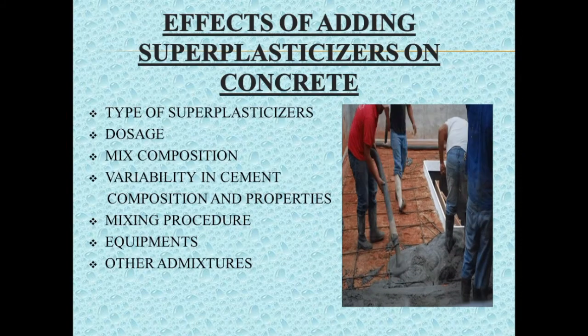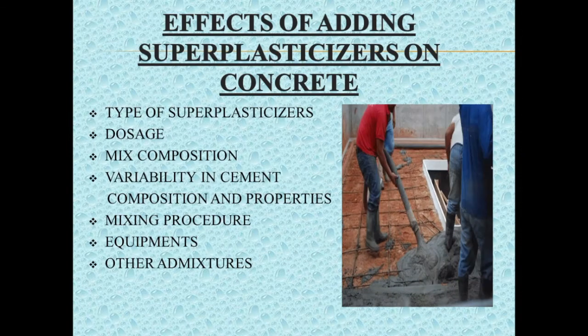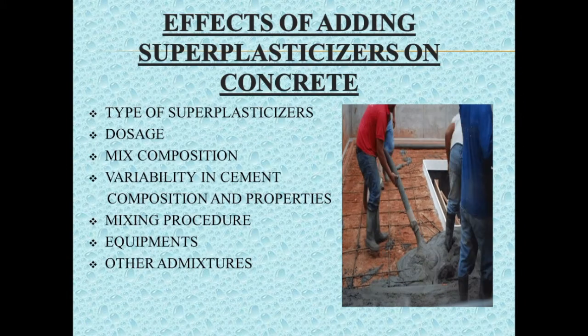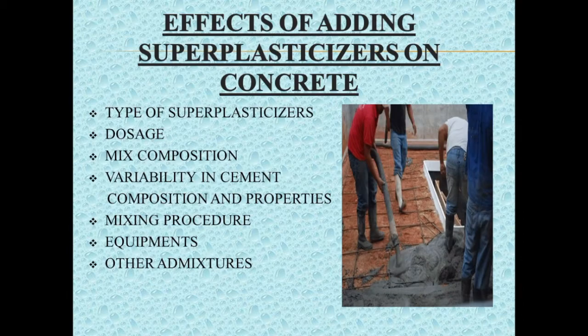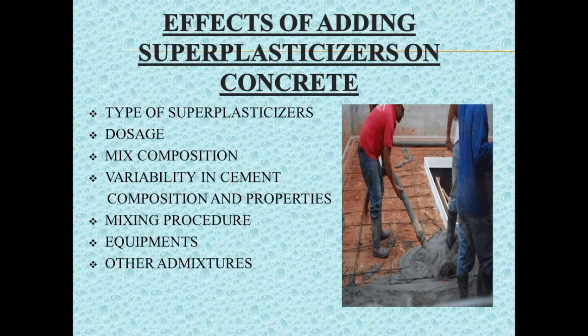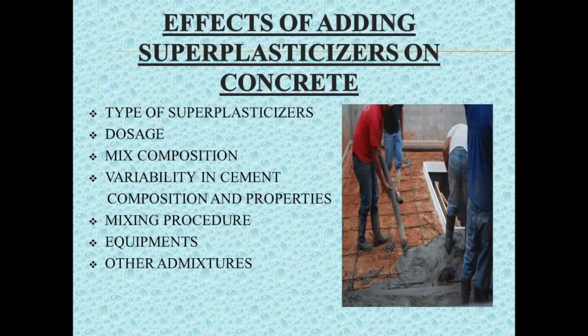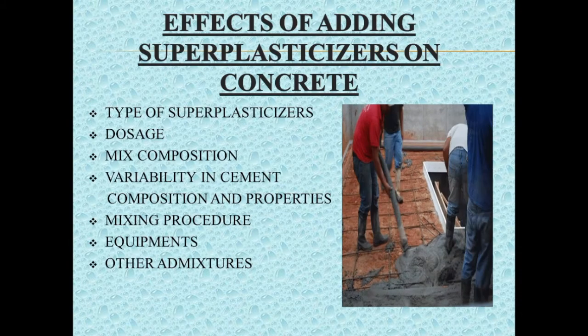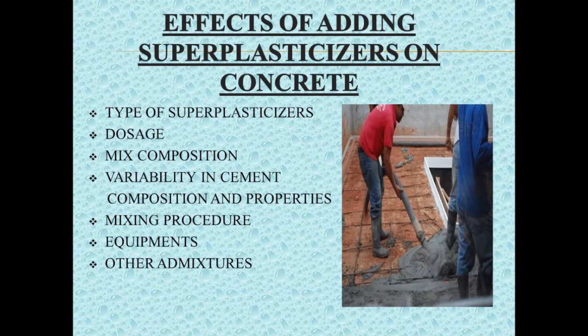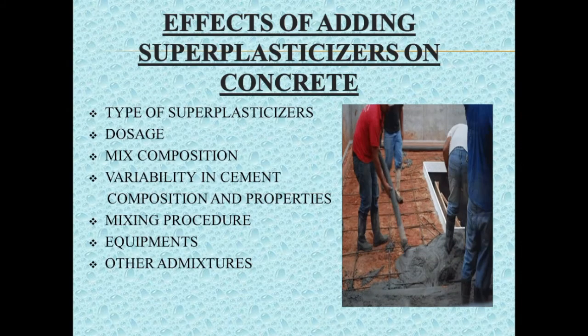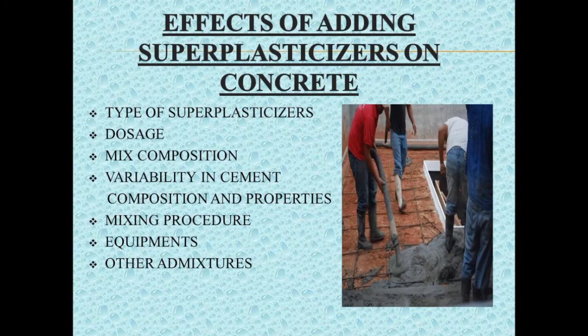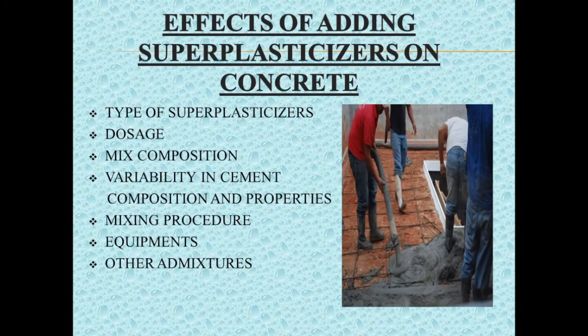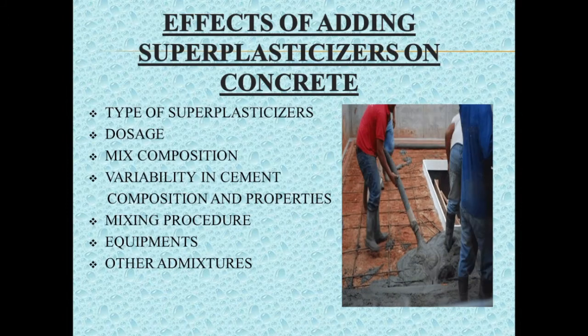The next factor is mix composition. The richness of mix and use of fly ash or silica fumes influences the workability of concrete — the better the mix, the better the dispersion of particles and hence better workability. The next factor is the variability of cement composition; usually the C3A content will have an overriding influence on the performance of superplasticizers.